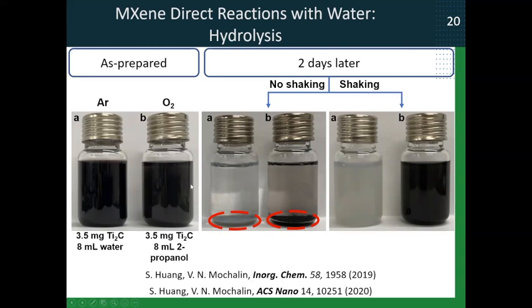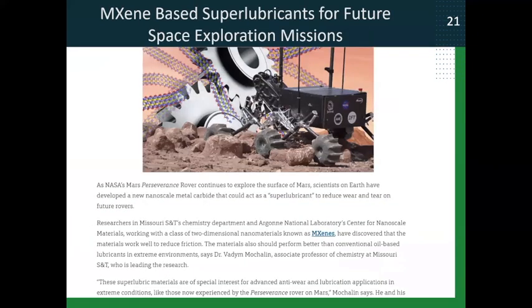This is just an example of how to suppress hydrolysis. If you simply change water to a non-aqueous solvent, then your MXene becomes much more stable, even if you saturate this solvent with pure oxygen, compared to water. Even when you degas water with argon, MXene degrades quite fast in water. So it makes sense to protect MXene with graphene if you want to use it in ambient environment.